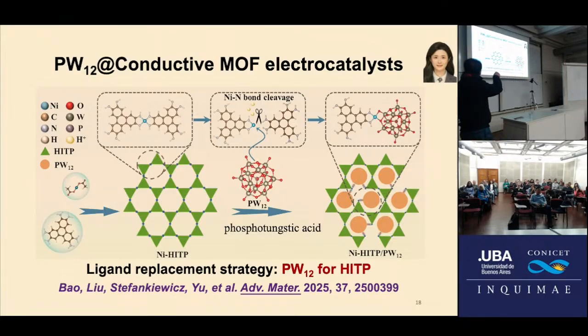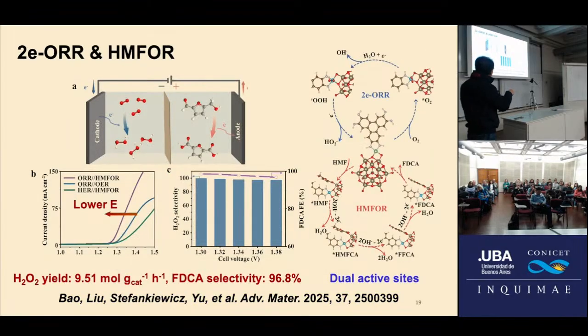This conductive MOF consists of nickel as a metal center and HITP as a ligand. After we construct this conductive MOF, we incorporate phosphotungstic acid into the pore channels. And by doing so, the electronic structure of the catalyst can be adjusted.